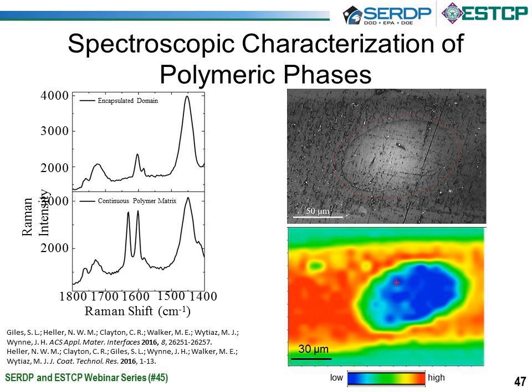I want to point out that as you go from the center of the domain outwards, you can see that there's a gradient. So it's obvious that there's a gradient in composition of the polymer out to the continuous film, and the continuous film is relatively consistent. Once we had this mapping, once we had the spectroscopic handle at 1632, we felt that we had the tools in hand to identify the composition of both the domain and the continuous polymer matrix film. And that's what we did in slide 48.